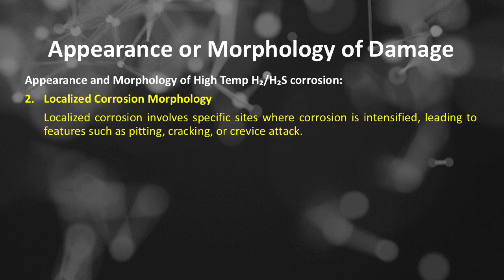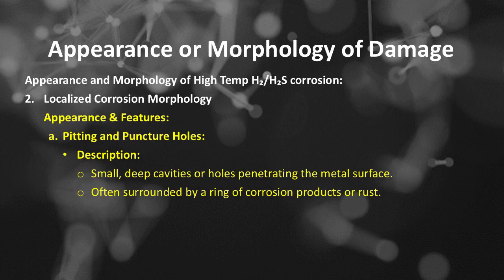localized corrosion morphology. Localized corrosion involves specific sites where corrosion is intensified, leading to features such as pitting, cracking, or crevice attack. The appearance and features of localized corrosion: number A, pitting and puncture holes, small cavities or pits, deep, narrow, and well-defined cavities or holes on the surface. Size distribution: pits can vary from microscopic to several millimeters in diameter, often dispersed randomly.